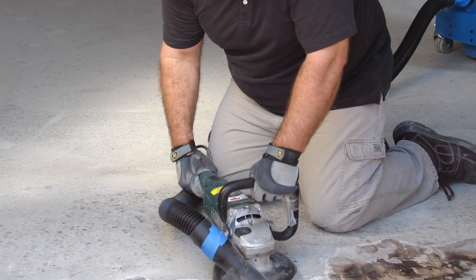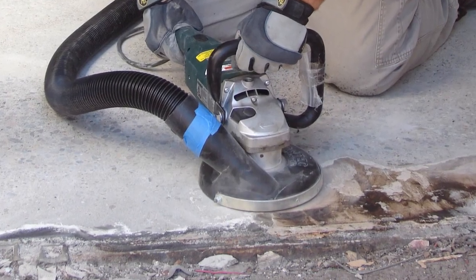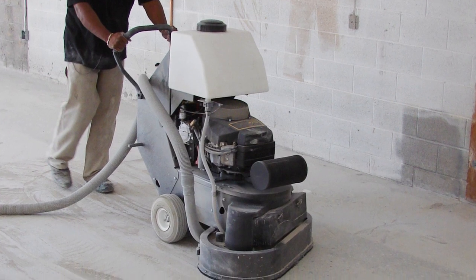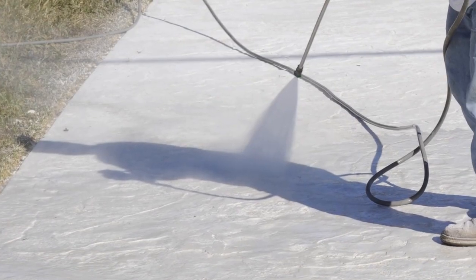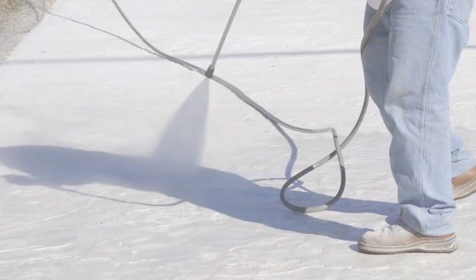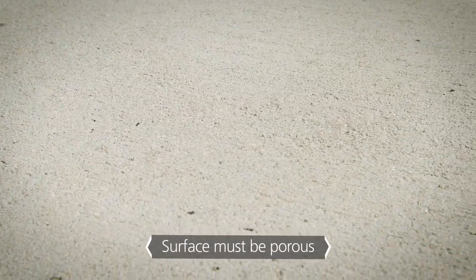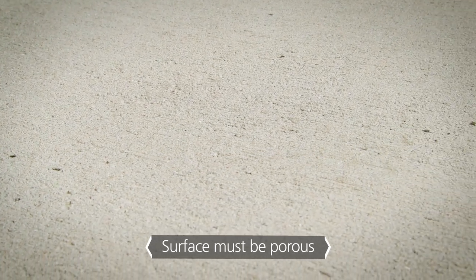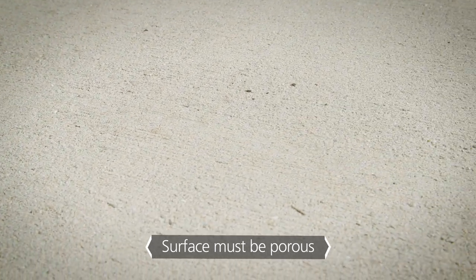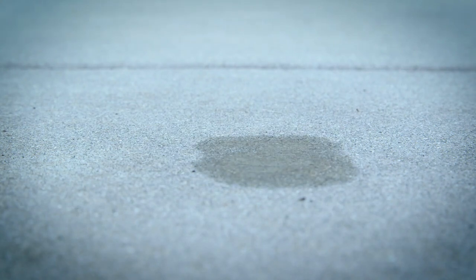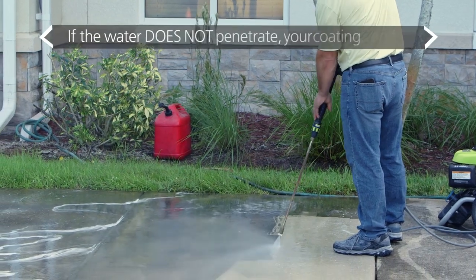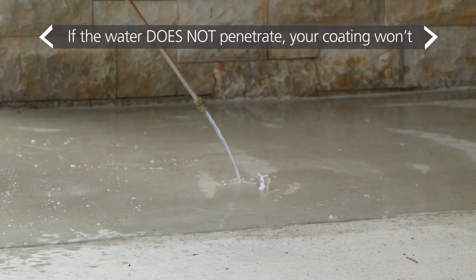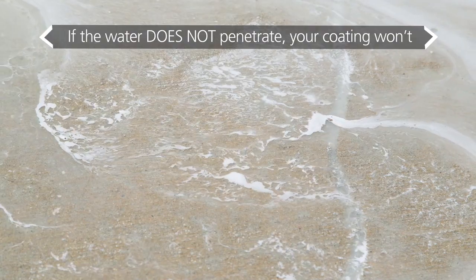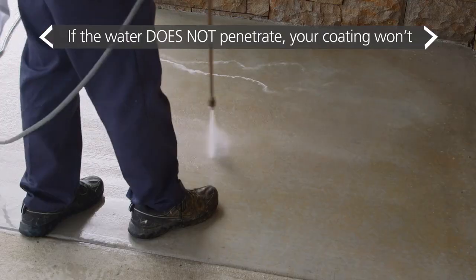If H&C Concrete Ready Etching Solution doesn't produce the necessary profile, mechanical abrasion is recommended. High-pressure water or surface grinding may be required to achieve the proper texture. It's equally important that the substrate is porous enough to absorb the new coating. You can confirm that with a water test. Simply drop a dime-sized drop of water on the surface. If it's absorbed within 10 to 15 seconds, you're good to go. If the water does not penetrate the surface, the coating won't penetrate either. Additional cleaning or etching must be done to remove any old coating or contaminant.